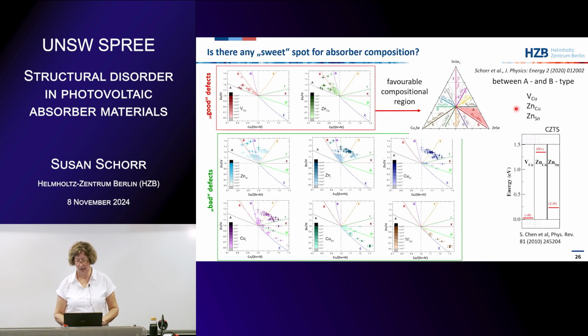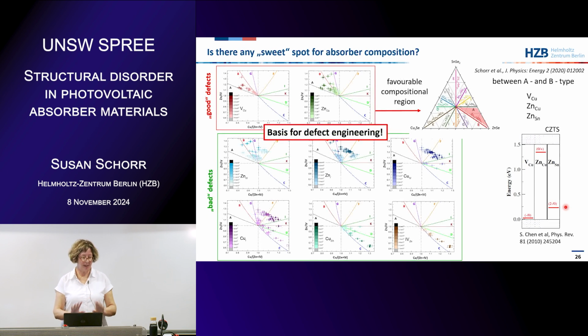So in this area you have mainly copper vacancies, zinc on copper and zinc on tin. These are the defects with the highest concentrations, and according to the calculations in that paper, copper vacancies are shallow, zinc on copper is also okay, and zinc on tin is not too bad. It's not a mid-gap defect. And now this is in principle the basis for defect engineering. Now you can work on the composition of your thin film.